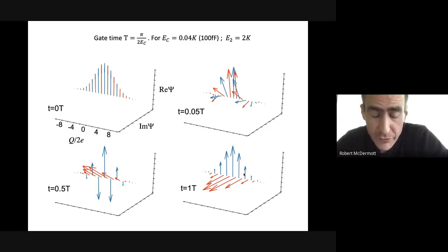Yeah. So it's exactly the same physics that you guys have been studying, and we're writing a paper on this right now. There are these burst events that we believe are due to absorption either of cosmic ray muons or gammas from low-level radioactivity in the laboratory. Those events are going to release hundreds of keV of energy, and most of that energy at the end of the day is going to go into a phonon reservoir. You're going to have high-energy phonons that are going to scatter down to the gap edge of the superconducting ground plane, and those phonons will break pairs and generate quasi-particle poisoning.